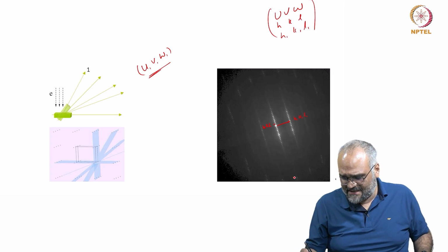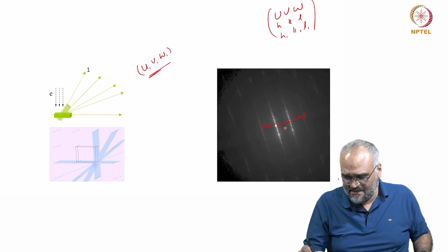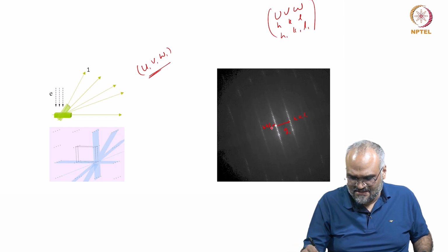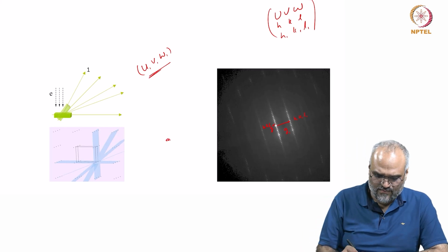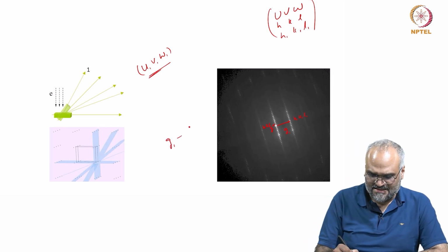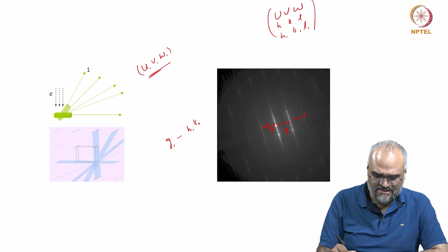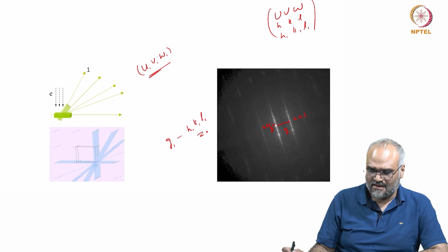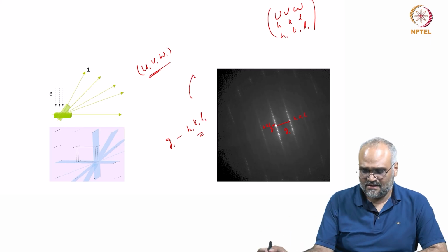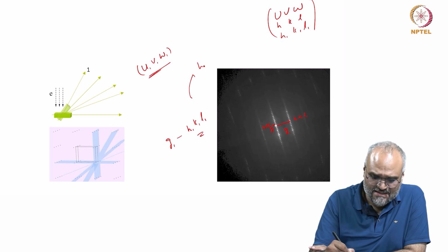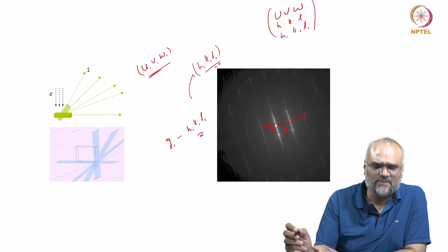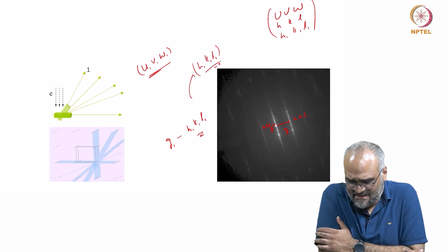So, if I think this is my unit vector, say G1, and if I call this G, if this unit vector G1 has reciprocal Miller indices corresponding to values H1, K1, L1, this would have come from a plane which is in real space with the same indices H1, K1, L1. That is what we established with the reciprocal lattice relation.